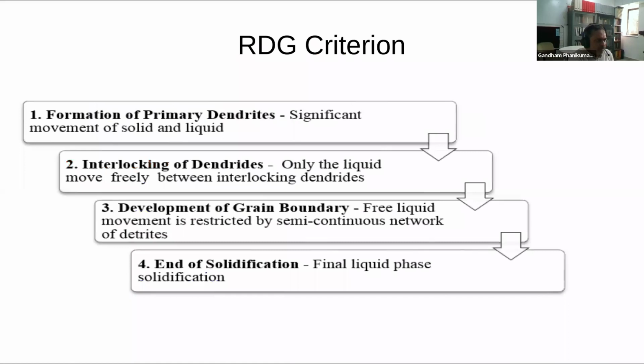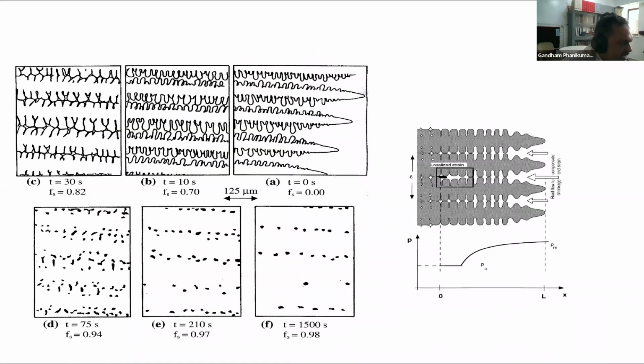Okay, so I move on to show you the physics of it here. You can see the dendrites that are growing and how the bridging is happening between the dendrites, and how the last-to-solidify liquid is available as islands, and how some of them may lead to porosity. Now, if porosity or cracks are going to occur, it is a very good idea to have them distributed over a long distance, rather than as one continuous segment, because a continuous occurrence of porosity is the same as a crack. So if at all you are going to end up with this kind of dendritic growth, one thing you should do is ensure that there are so many bridges that the liquid pockets are distributed along the length, very broken and not connected at all, which means that a fine dendrite microstructure will help you.